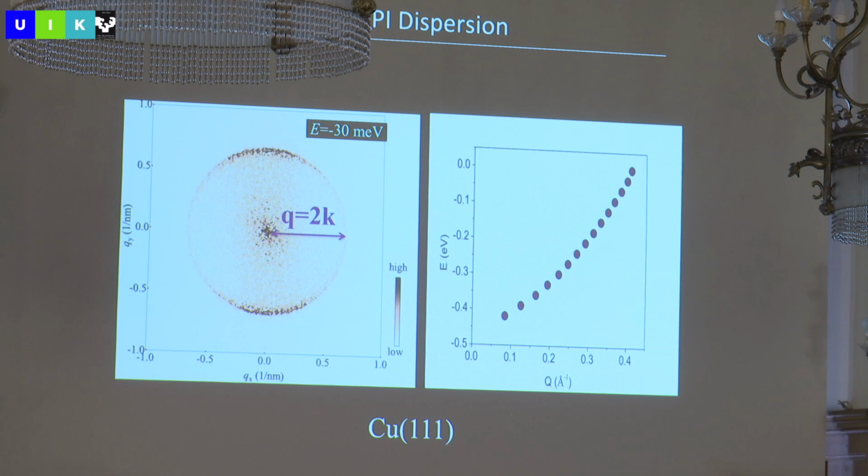That's electron-phonon coupling. You can see the wiggles due to electron-phonon coupling from this quasi-particle interference. You can even invert those wiggles and get the real part of the self-energy due to electron-phonon coupling using this technique. So our energy resolution is very, very good.